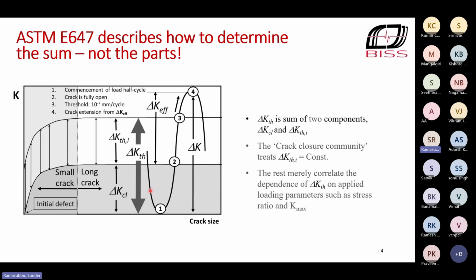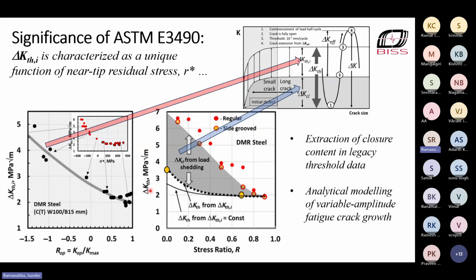Now, the new standard, looking ahead, E3490, which Vikram introduced very nicely in the beginning, determines the intrinsic component. And it turns out that the intrinsic component is very sensitive to a near-tip stress parameter, which is plotted here along the horizontal axis. And you can see along the vertical axis that ΔK threshold intrinsic can change quite a bit depending on this computed value of near-tip residual stress. And this is the plot that ASTM E3490 helps you determine. It specifies a reproducible, highly reproducible test method to obtain this relationship.